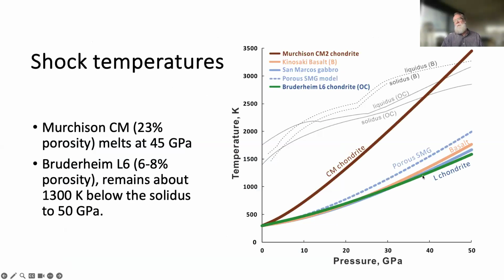These are his results, and there are a couple things that are interesting here. Again, I'm showing the liquidus and solidus curves for Murchison in the gray, and the dashed ones are for Mare basalt. And these are the conditions. Well, let's do the CM chondrite first. The CM chondrite has a high porosity, and porosity generates heat during shock. It's probably the biggest controlling factor in producing melt pockets and melt veins, the collapse of pores and fractures. And so this, with a high porosity, gets very hot and is completely melted by 45 gigapascals, right?